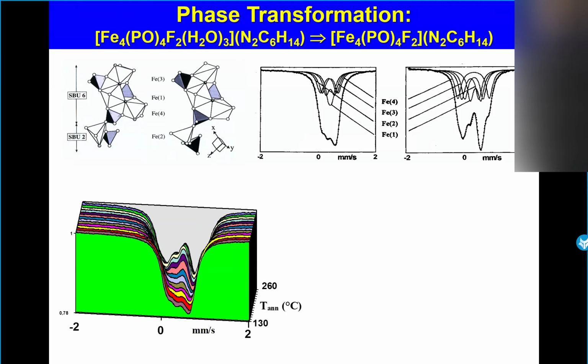Because, as I maybe did not mention this morning, the time to get the spectrum might be from 15 minutes up to a few days. It depends on the content of the sample, on the complexity of the structure. So what we are doing now, we were using the cryofurnace, because if we do an experiment, for example, at 100 Celsius, and then at 120, probably during the registration, we will accumulate different states. So the idea was to go to one temperature, to stay 1 hour, and to go down to 77 K, and to compare the different hyperfine structures for the different temperatures. Okay? And this is given there.